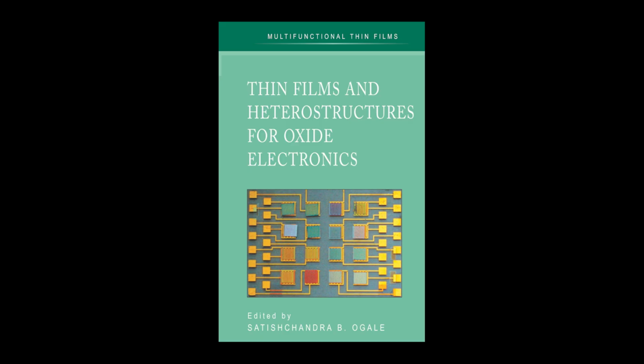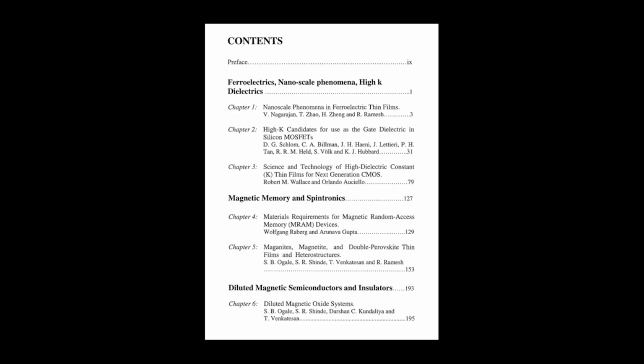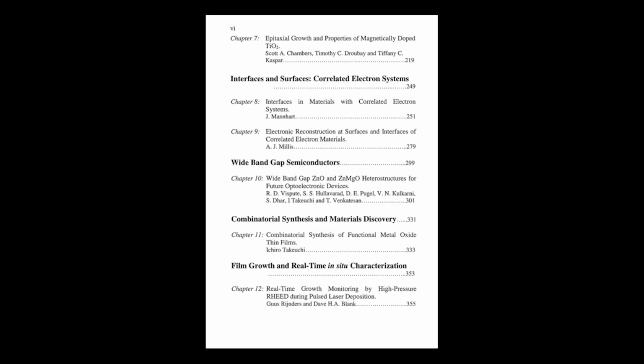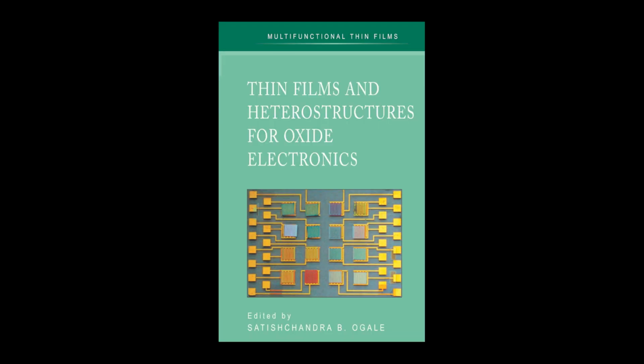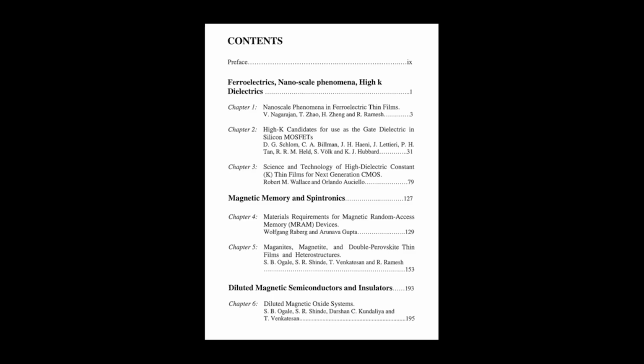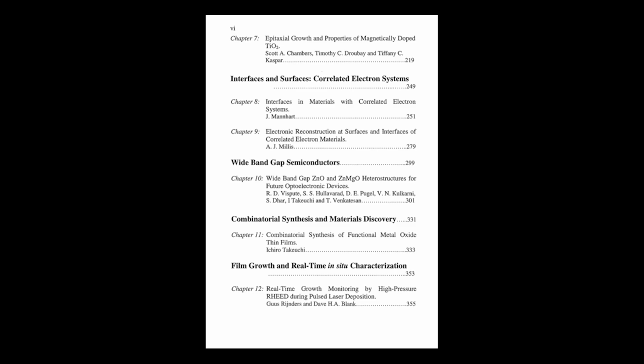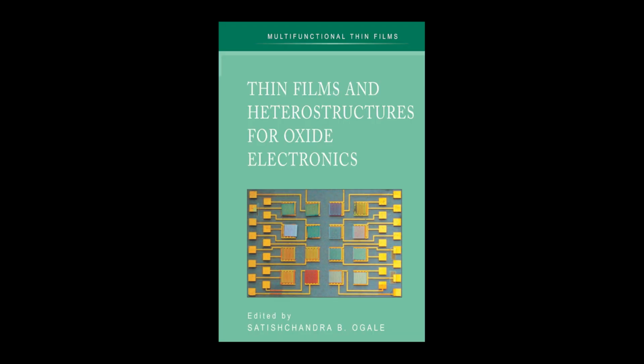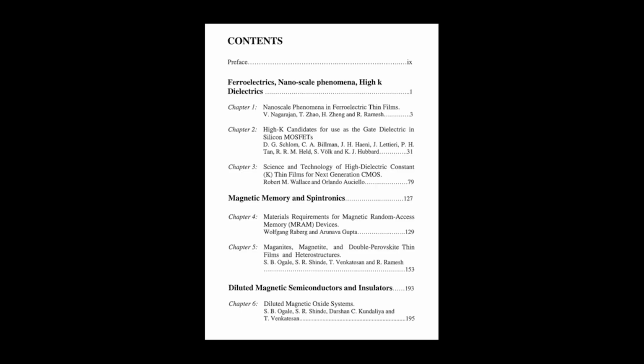The field must have fractured. Believers versus skeptics. Completely. You had groups convinced intrinsic FM was real, driven by complex physics, and others arguing pretty much all reported room temperature FM in these systems was just due to undetected nanoscale clusters. Okay, if the simple idea of free electrons mediating the magnetism, like the RKKY interaction, was problematic because of clusters or maybe just not enough free electrons in many samples, how did researchers explain the ferromagnetism seen in films that were actually quite insulating, films that didn't have many free carriers? That forced the community, particularly the theorists, to come up with a totally different model, described in Chapter 7. This model works even in insulators, F-center mediated exchange. F-centers. Those are related to the oxygen vacancies again, right? Exactly. An F-center is basically an oxygen vacancy that has trapped one or two electrons, the electrons left behind by the missing oxygen ion.